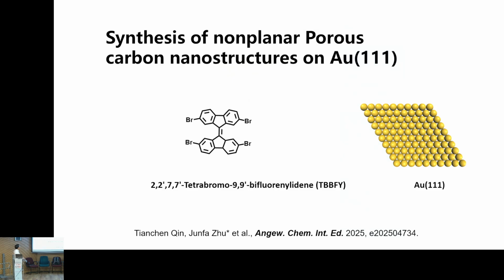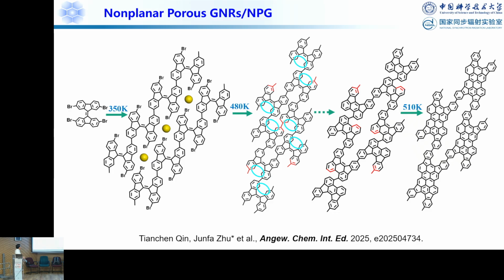So the last example I want to show here, we use this precursor molecule. Why did we choose this one? Because if this double bond becomes a single bond, then this will be a six-membered ring here, and you probably form this open-shell structure. So we put it on the gold surface, and you can see when you heat up, the precursor molecules stay on the surface like this.